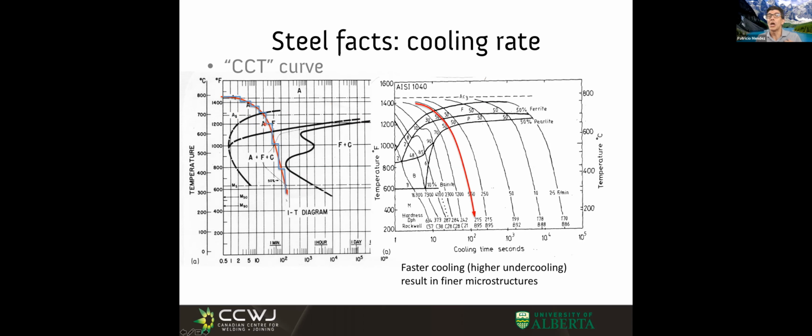Fine, but I know what it is. Here they put only F, but I know that this means above this line I have only austenite. To the right of the line, I start to have primary ferrite appearing. Look, here it says F plus C, being not very committed to whether it's pearlite or bainite. And here they tell me, aha, P, pearlite. Pearlite starts to appear.